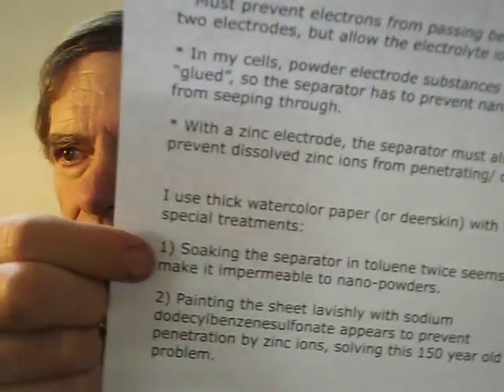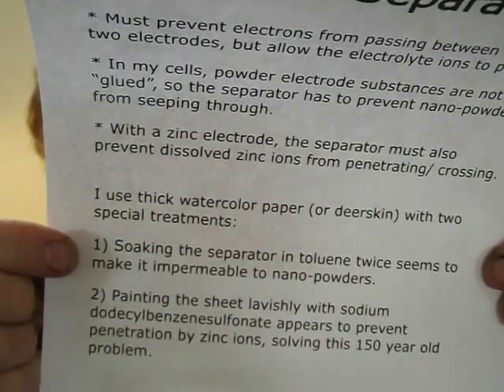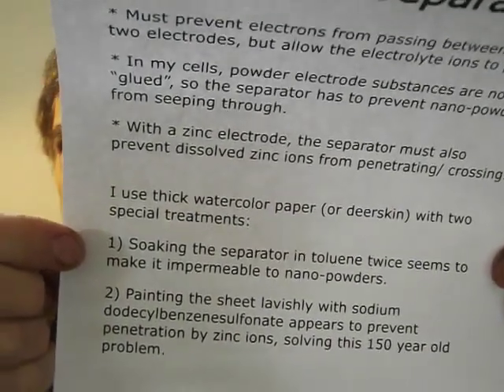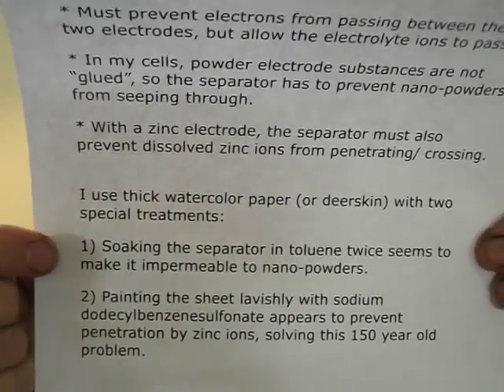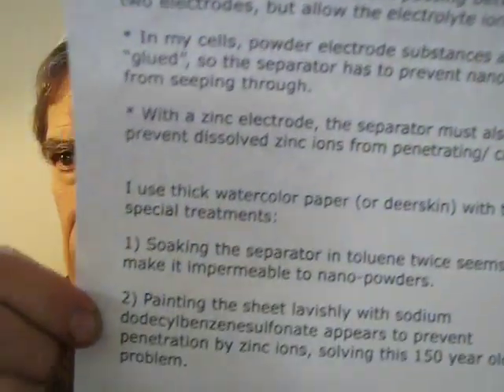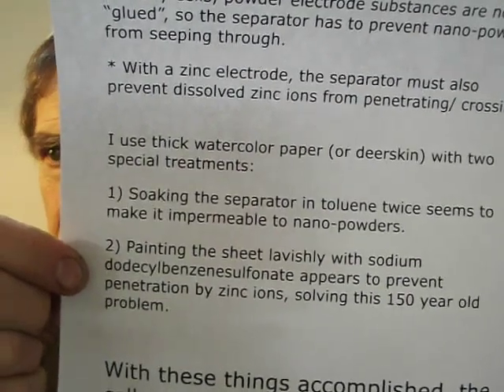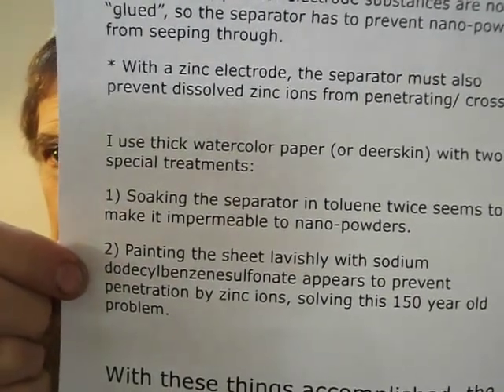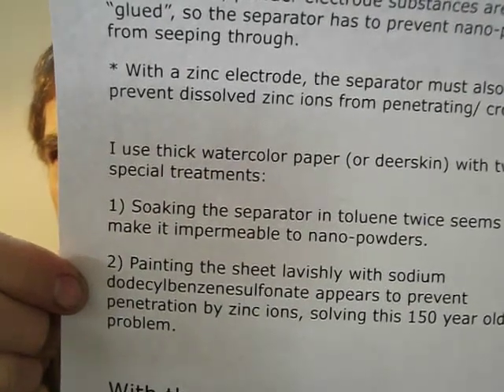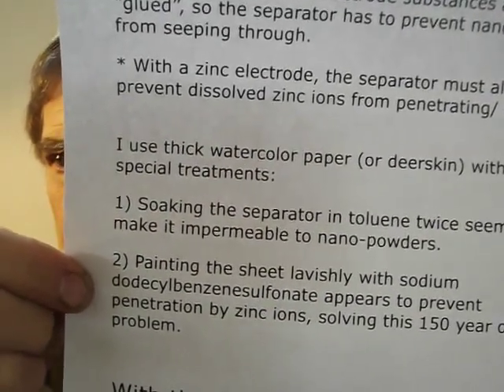Then there's two special treatments. The first one is I soak the separator sheet in toluene twice and then let it dry. And I'm not quite sure why, but that stops the nanopowders from penetrating the separator sheet, so they can't get through and short to the negative electrode. And then I paint the separator sheet with a mixture of sodium dodecylbenzenesulfonate in water, and that seems to prevent the zinc ions from going through or penetrating the separator sheet.